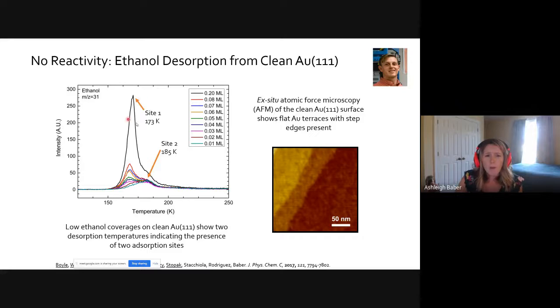As we start with very, very low coverages, we can see a saturation of this small peak where you have the desorption at about 185 Kelvin. After the saturation of that peak, then we see the growth at 173 Kelvin. This will continue, as you see in the next slide, up to higher and higher coverages. But here we're maxing out at only 0.2 monolayers of ethanol on the surface. Looking at this, at first we're like, okay, what's going on there? But thinking it's probably a different adsorption site on the surface.